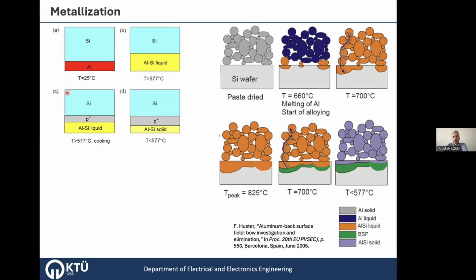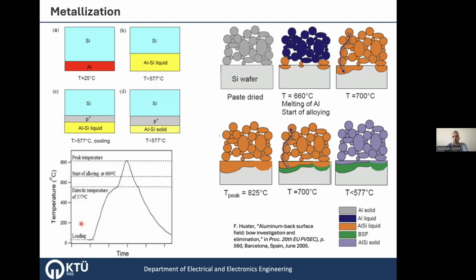So what we do is screen print the aluminum on the surface of the silicon wafer at room temperature, and with the appropriate profile like this, here's an example, the alloying of aluminum and silicon starts around 660 degrees, and with the temperature increasing further, when it comes to the peak, you have fully liquid aluminum inside the silicon, and when it cools down very fast, and you can change this profile, but the shape is very similar, you will see that the solidification takes place, and you have a P plus BSF here, and the residue of the aluminum on the back side as the contact.